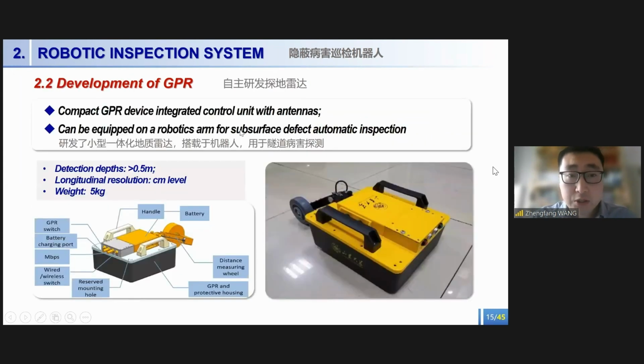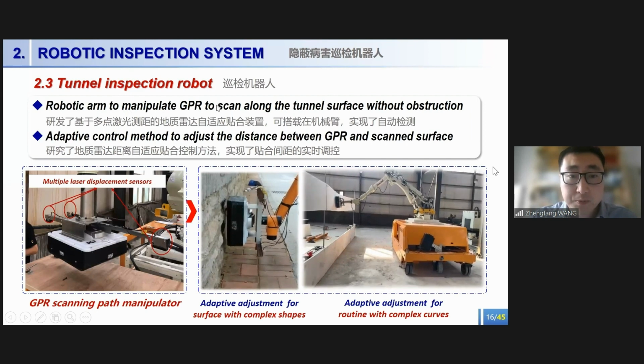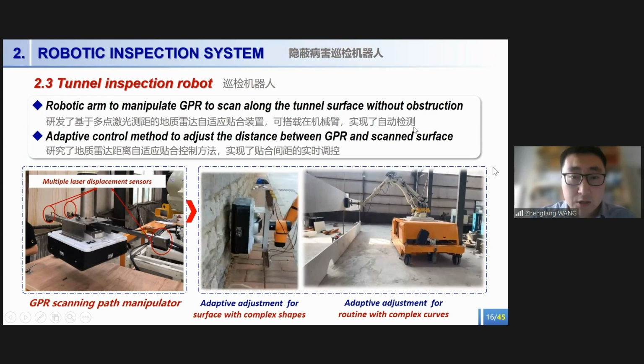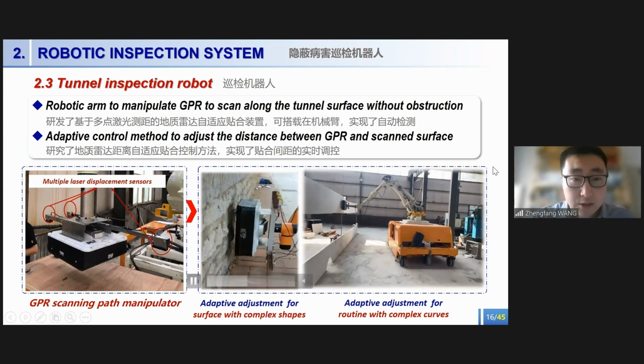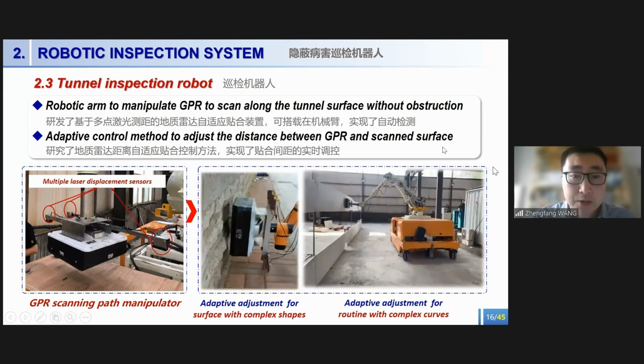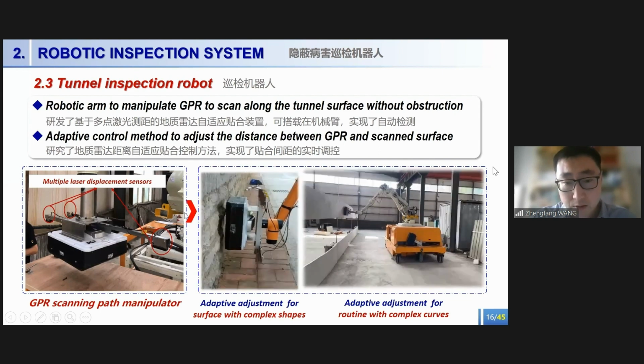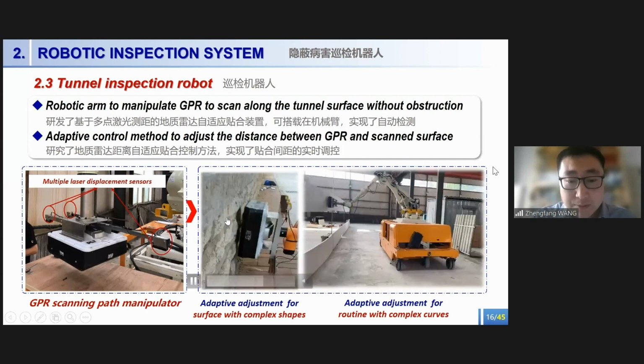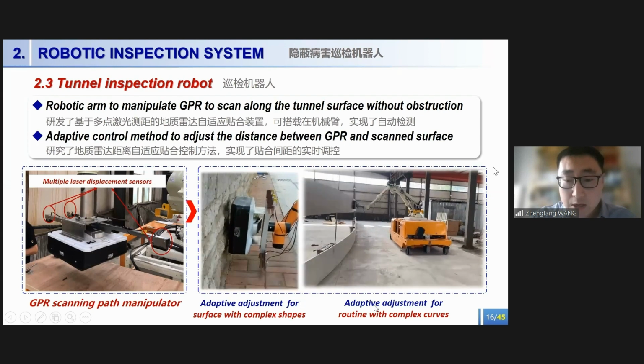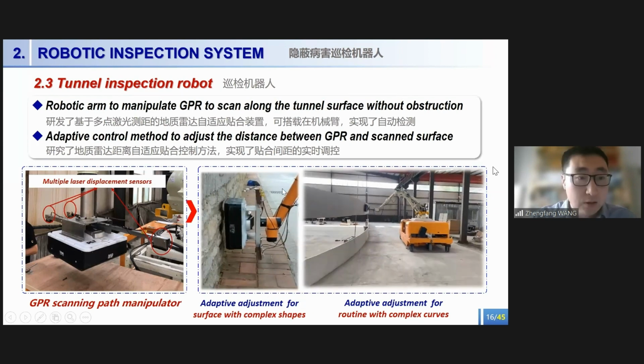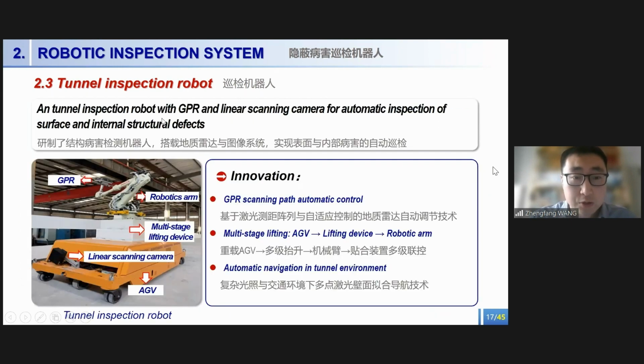Then we have developed our own GPR device. It is a compact GPR device, integrating the control unit and the antennas. This device can be equipped on robot arms for automatic inspection. We utilize the robotic arm to manipulate the GPR to scan along the tunnel surface without obstruction. The key technology we have developed is an adaptive control method to adjust the distance between the GPR and the scanned surface based on the information collected by multiple laser displacement sensors. Then the system can adaptively adjust the GPR for surfaces with complex shapes and for routing with complex curves. We have developed the tunnel inspection robot, which is equipped with a GPR and a linear scanning camera for automatic inspection of the surface and internal defects, and it is being applied.